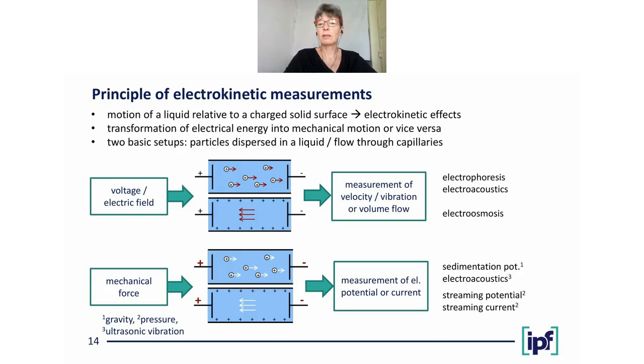Depending on the experimental setup, we either apply a voltage or an electric field to create a motion of the particles or of the liquid through the capillaries, and then measure the velocity, the vibration of the particles, or the volume flow. These are methods called electrophoresis, electroacoustics, electroosmosis. On the other hand, we also can apply a mechanical force, as for instance gravity, pressure, or ultrasound, and create the motion in this way. And then we can measure an electrical signal, an electrical potential or current. This is done in methods like sedimentation potential, electroacoustics, the other way around, or streaming potential and streaming current.